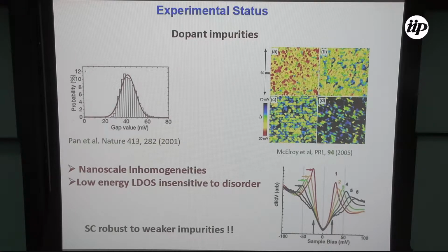Interestingly, if you look at the density of states of different regions, say the red region, which is this curve, and the black region, which is this curve, they have different gaps, and as a result, they have different positions for the coherence peak. But interestingly, at low energy, the density of states is quite robust to impurities. You take the density of states from different regions of the sample which have different dopings, but the low energy density of states is robust.